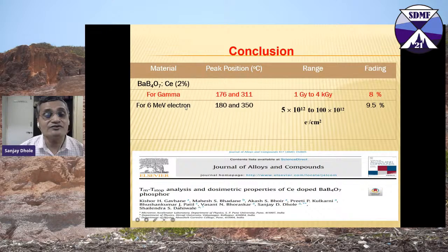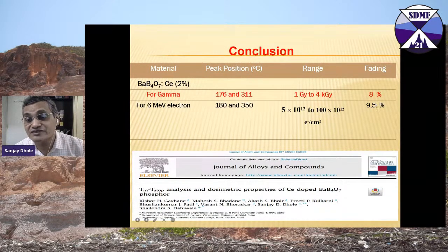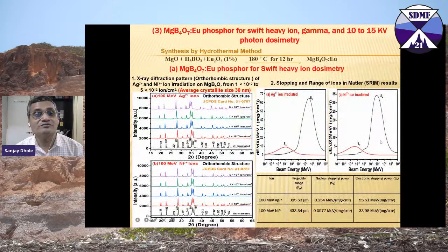And for 6 MeV electron, it is the peak positions, but you can vary from 5 into 10 power 12 to 10 power 14 electrons per centimeter square. So you can always convert, and that goes up to 1 kilo gray also. But again, if you see that the fading is less than 9.5%. Okay. So this we could publish in Journal of Alloys and Compounds.